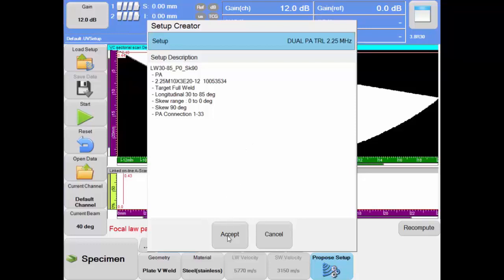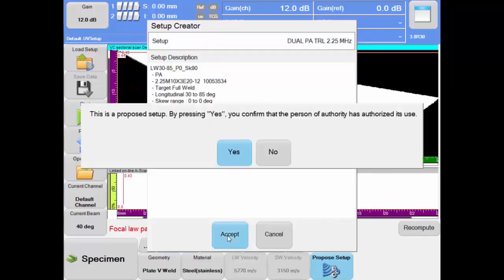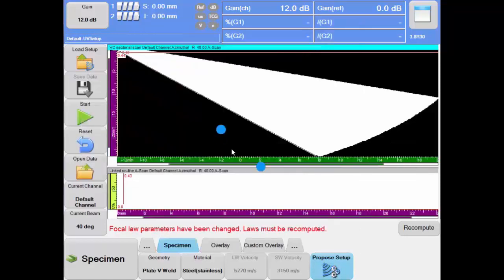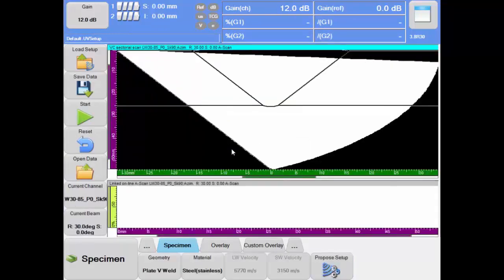As soon as the operator selects an inspection technique, the software will show a more detailed description, and when the operator accepts and confirms his agreement with the proposed configuration, the probe, the wedge, and the basic UT parameters will be automatically set to values that allow for optimum detection capability and complete coverage of the examination volume. The content of the proposed setup feature can be overruled by the operator, and it can also be permanently modified to comply with specific company work instructions.